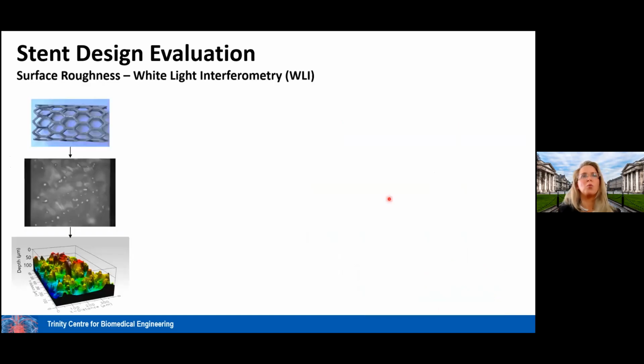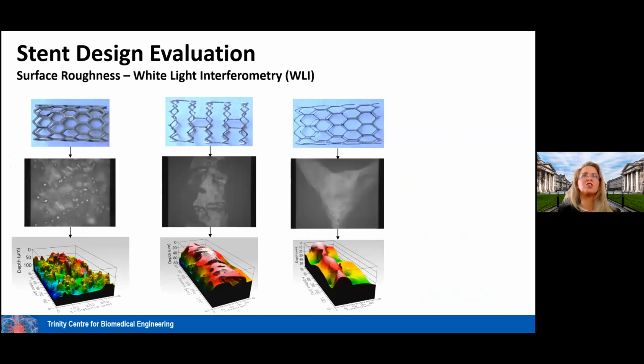But now we can see that this controlled reduction in strut thickness can be achieved, and we can also achieve, at the same time, which is really beneficial, a good surface finish. We used a technique called white light interferometry to look at the surface finish of each of those stents. So before, the as-print with all the defects, and you can see that here, all these peaks represent little particles that are attached onto the surface.